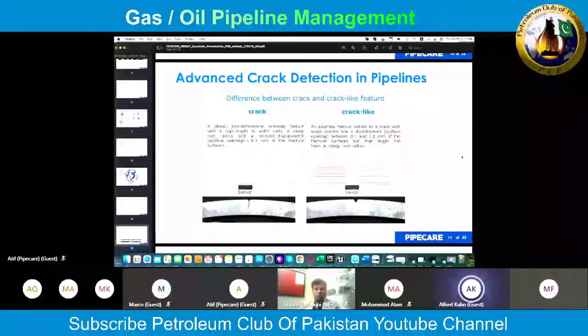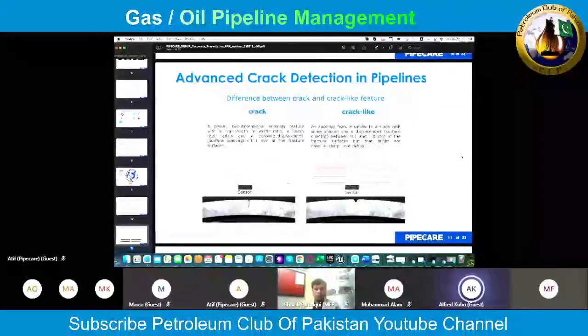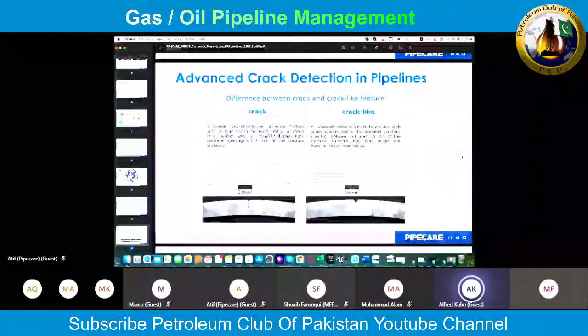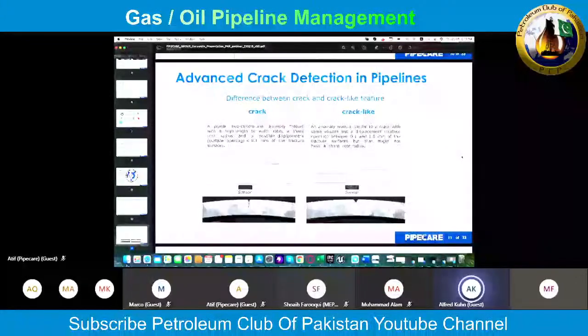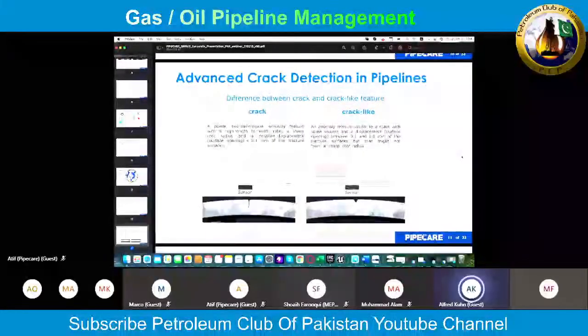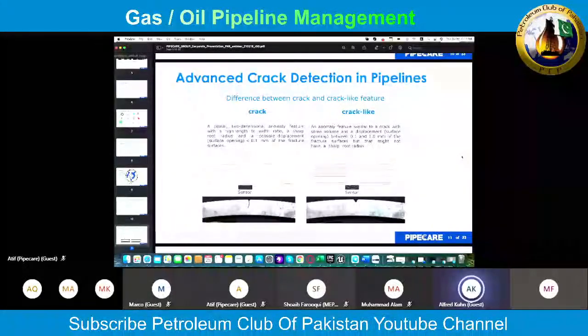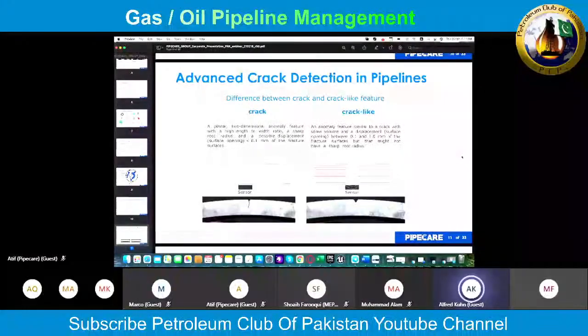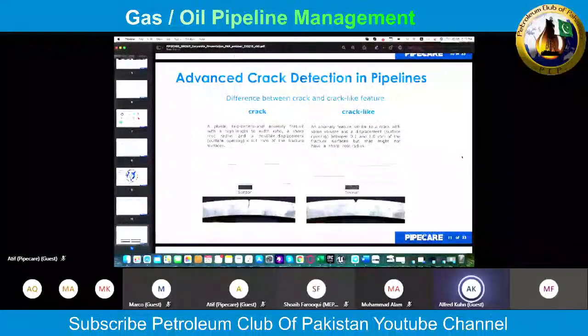You also see these pictures of real features which have been cut and examined in a lab. On the left picture, you see a metal loss feature on top and then a crack protruding into the pipe wall. The magnetic tool would see the metal loss feature, but not the crack.